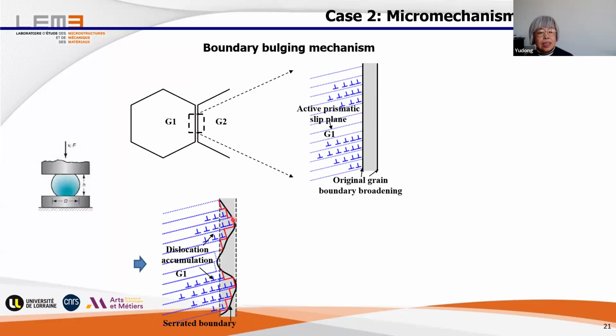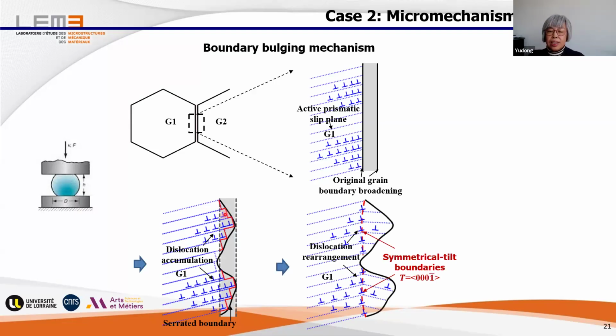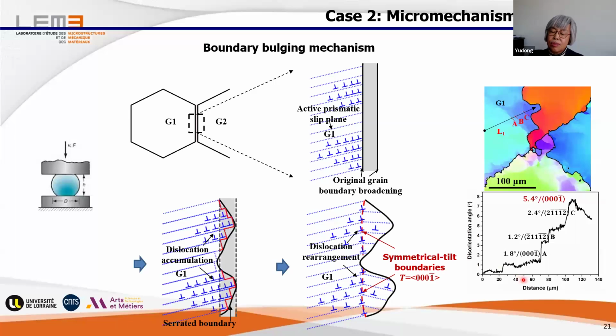But in any case, such a dislocation configuration is not energetically economical. And so with the thermal effect, the dislocations will climb to form such a low energy configuration. And this is called polygonalization. And this corresponds exactly to what we saw before in the bulging area.